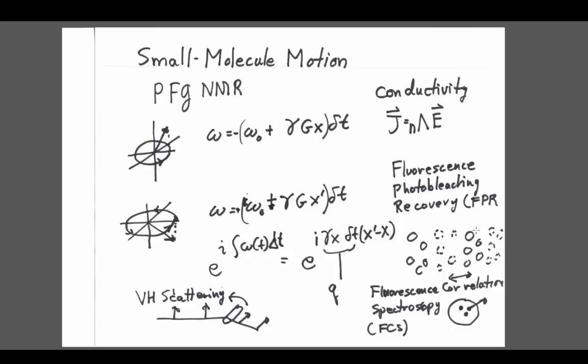Soon after the original FCS, fluorescence correlation spectroscopy papers came out, I wrote, I believe, the first paper not written by the original creators of the technique, a paper explaining that FCS could measure both D_M and D_S depending on what fraction of the particles were labeled. If all of the particles were labeled, you measured the mutual diffusion coefficient. If only a few particles were labeled, you measured the self-diffusion coefficient. That prediction was actually confirmed by Skalatar much later. It's a very pretty experiment, and it shows that my predictions were correct.